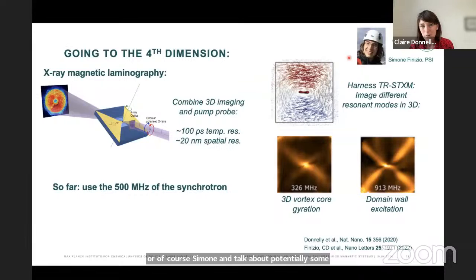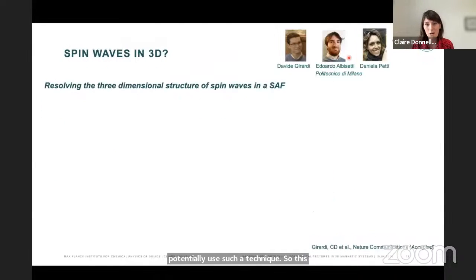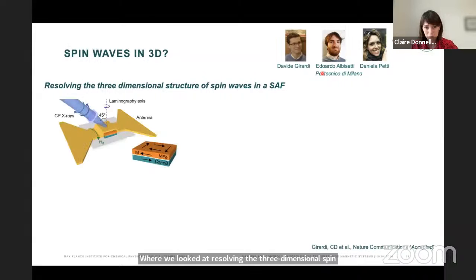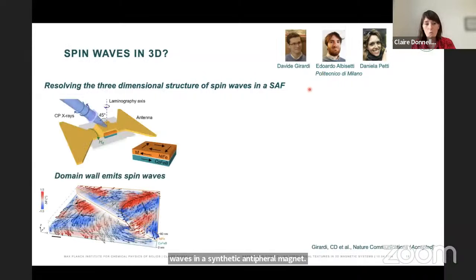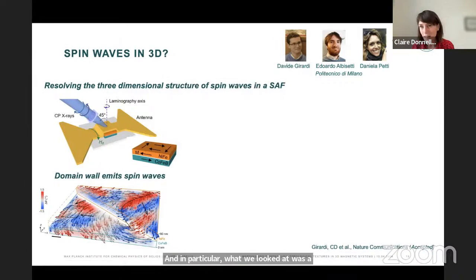Now, just to give you an example of how you can potentially use such a technique, so this resonant dynamic imaging in 3D, we've recently had the pleasure to work with Davide Girardi, Edoardo Albisetti, and Daniele Petti from Milan, where we looked at resolving the three-dimensional spin waves in a synthetic antiferromagnet. And in particular, what we looked at was a Landau pattern again, where the domain walls in the vortex core in the Landau pattern leads to the emission of spin waves in the synthetic antiferromagnetic system.